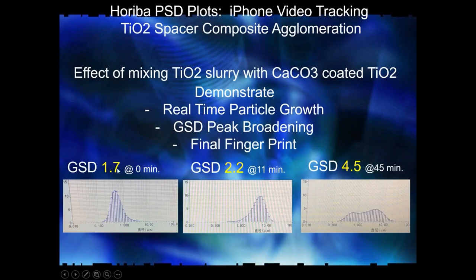GSD of a 1.7 looks like this. A GSD of 1 would be a stick going straight up. So in other words, the square root of the D85 divided by the D15 is 1. The square root of 1 is 1. So that is the ultimate. Nobody can make that, at least commercially. So at the 0 minute mark, we're at 1.7, and then it starts growing in 11 minutes. And then at 45 minutes, the reaction, because we've added chemicals to purposely agglomerate it, is done.